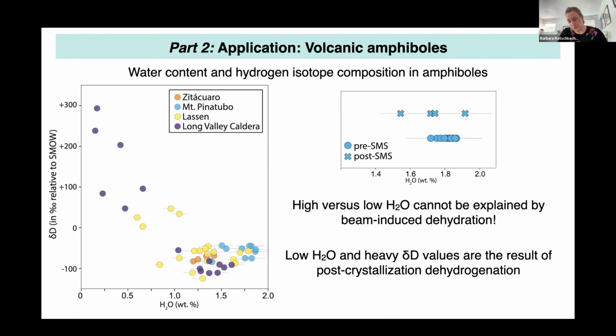So one concern we had at the beginning is that potentially beam-induced dehydration is something which could lower the water content in the amphiboles or potentially oxidize the iron. So in order to test that, we analyzed the water contents in individual amphiboles prior to exposure to synchrotron radiation and after. So this is shown here at the right, where we again look at exactly the same grain and their water content before exposure and after exposure. And there's no difference within uncertainty, so we're quite comfortable saying that the low water contents and the heavy hydrogen isotope composition we see in some of the amphiboles from Lassen and Long Valley are actually due to post-crystallization dehydrogenation.